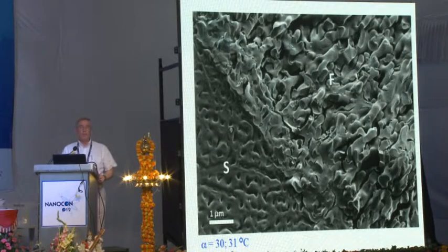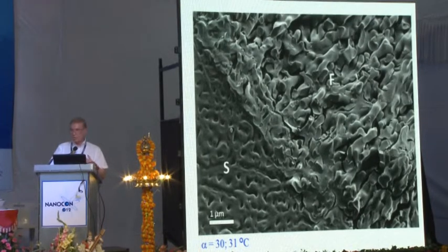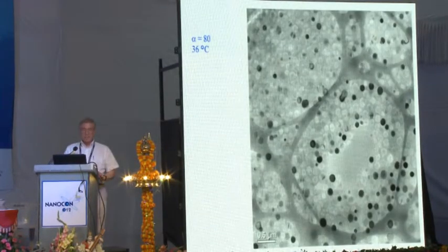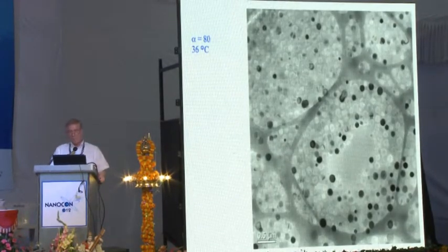If we go now to the alpha 30 and temperature of 31, you see that we get the sponge-like structure, which is characteristic of a bicontinuous phase. And this was something that we tried to do for a very long time. And in fact, now we can do it both by TEM as well. Here you have the same structures by TEM.